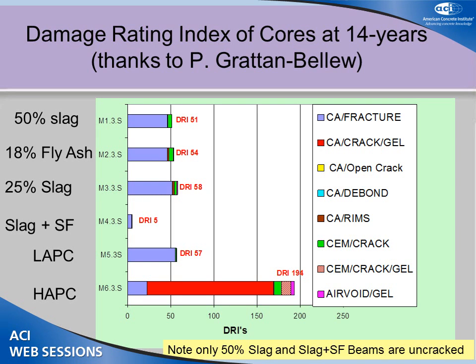Okay. We also did some petrographic work on the cores that we took at 12 years, but we measured them at 14. Took us a while to get our act in gear. Paddy Grattan-Bellew up in Ottawa did the damage rating index, where he does a petrograph.